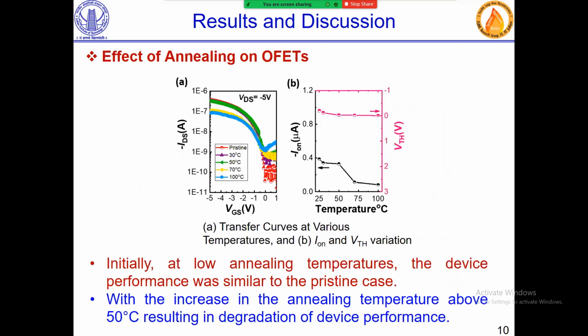Effect of annealing on OFET. Initially, at low annealing temperature, device performance was similar to the pristine case, as you can clearly see from figure A. With increase in annealing temperature above 50 degrees Celsius, there is deterioration in the performance of the device. As you can see in figure A, when I increase the temperature above 50 degrees Celsius, the current decreased. Figure B is extracted from figure A, in which the Ion decreases as the temperature increases, and there is a shift in the threshold voltage.